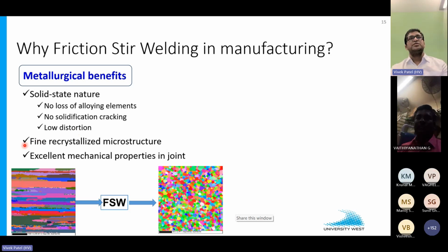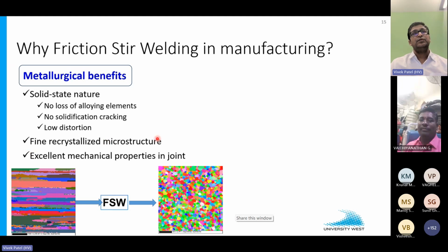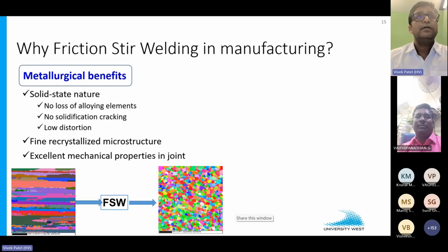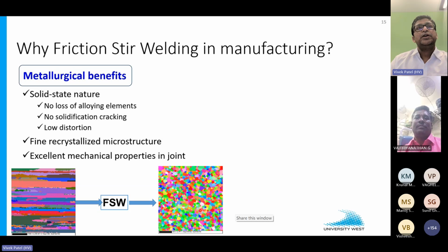And due to the plastic deformation, you get a very fine recrystallized microstructure. Here you can see the EBSD map of a 7000 grade of aluminum, 7075 T6 condition. This is the parent material, and after the weld, if you see the weld nugget, this much grain refinement you can have. This grain refinement is happening from the elongated pancake grains of rolling to fine equiaxed grains, and this is nothing but because of the plastic deformation. There is severe plastic deformation happening during the process, and that gives you the fine structure.